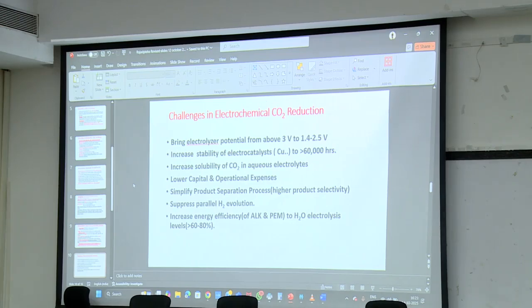Next slide. Challenges in electrochemical CO2 reduction. The electrolyzer potential for CO2 now is about 4 volts. We want to reduce it to the value for water. For the water electrolyzer, the potential is 1.1. At that value it becomes more attractive. But at present it is about 3 to 4. Increase the stability of the electrolyzer, there are hardly 5,000, 6,000 hours. That needs to increase to 60,000.